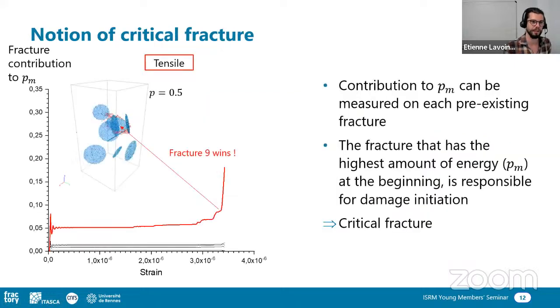This is what we can see here on this kind of test, which is a tensile test with a few fractures. You can see here the blue dots are the subcontacts that belong to the fracture with fracture properties, and in red you have the subcontacts from the matrix that failed to become crack subcontacts. And each line here represents the fracture contribution to the global PM value. You can see that in the elastic regime, all the values are constant, but as soon as I start to break around the fracture, this value is increasing, and increasing a lot in the end, because the damage is progressing quite fast.